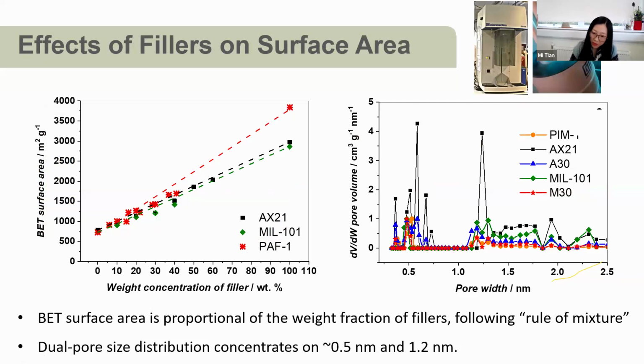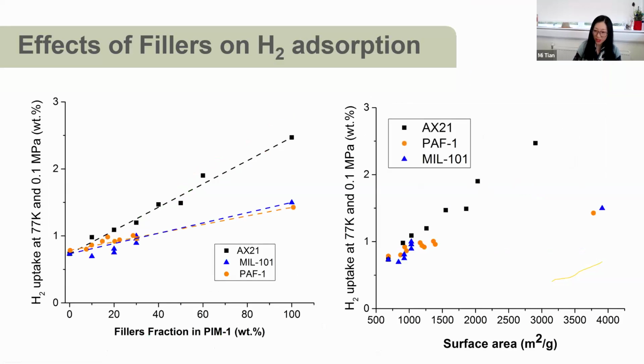So then we measured the BET surface area, specific surface area, and that is a key indicator of how good the material's adsorption capacity is. So we can see the surface area increases, has a linear correlation with the fillers concentration, which follows the rule of mixture. And the majority of pore size is less than or around 1 nanometer. So it all follows our design.